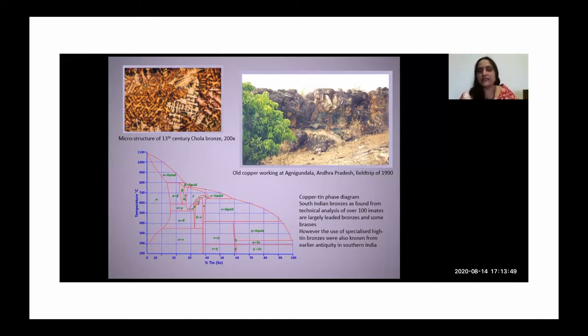And that is also indicated by the copper-tin phase diagram, which shows that at less than about 15% tin, the tin goes into solid solution in bronze to form the alpha solid solution. But the artifact that I showed you in the last picture, that vessel, is made with a bronze of about 23% tin. Now, what would happen is that when you keep adding tin to bronze, it actually gets more brittle. So it's not a very workable alloy. But as I will mention, at this particular composition of 23%, if you look right up and come to a temperature range of about 600 to 700 degrees Celsius, then you get the formation of this beta phase, which is indicated by the Greek letter beta.